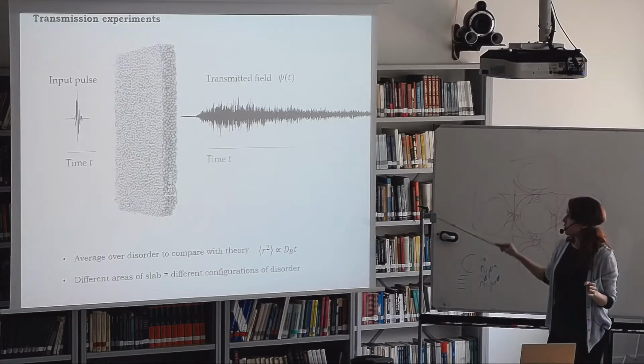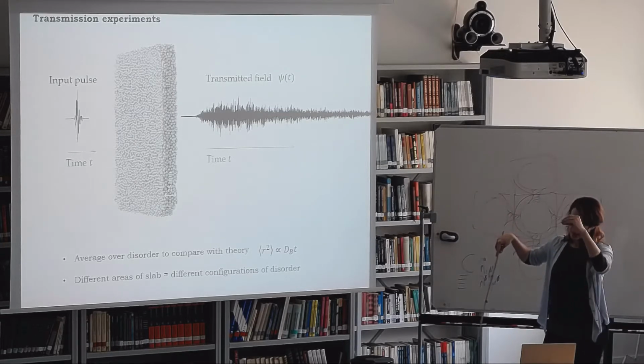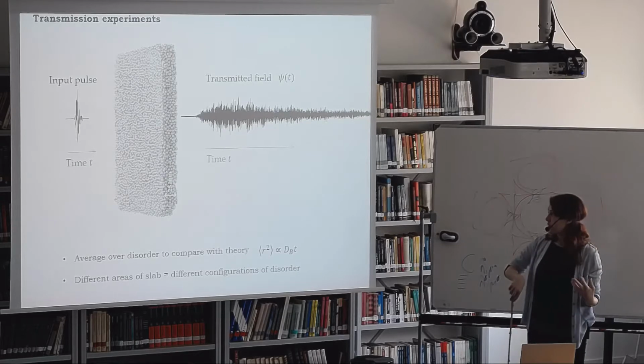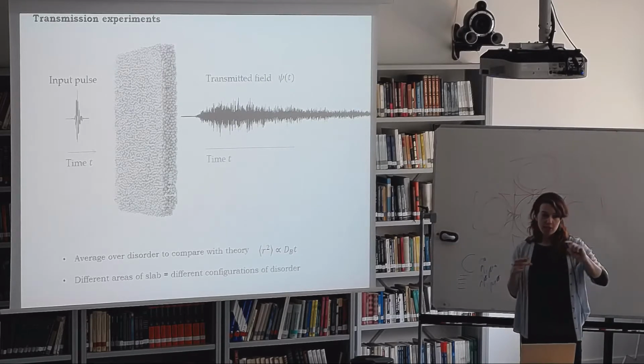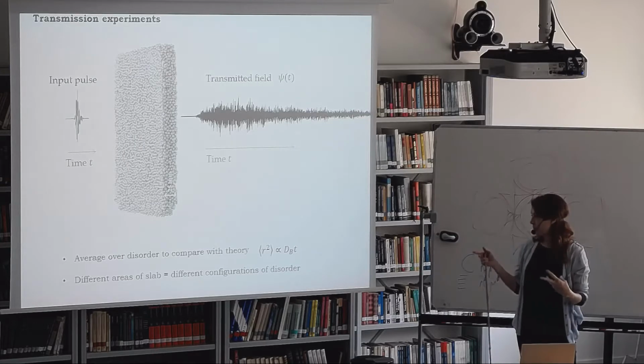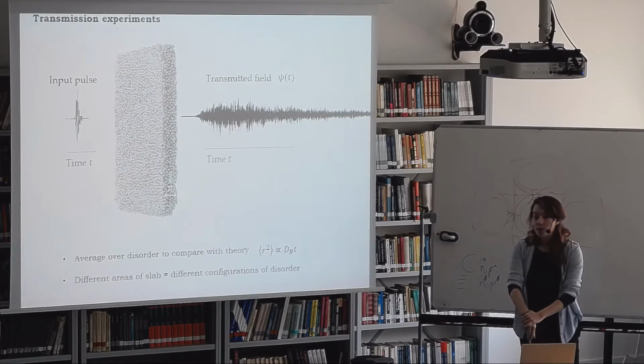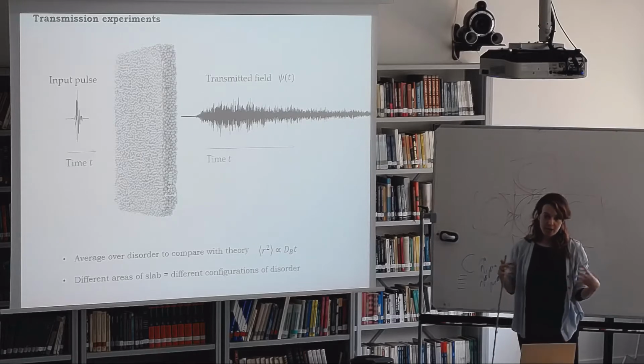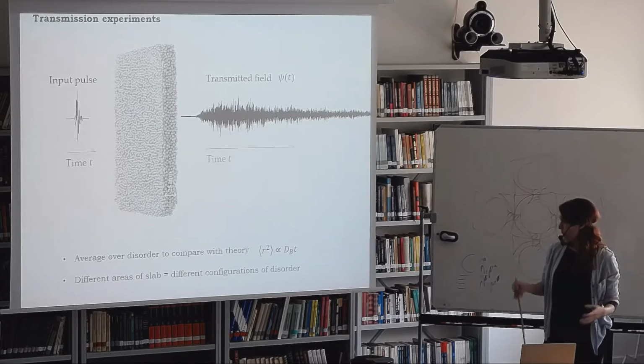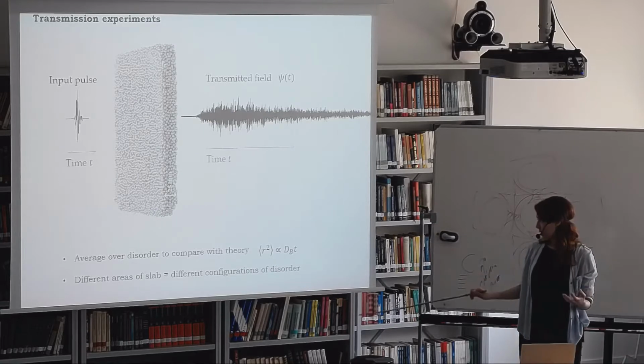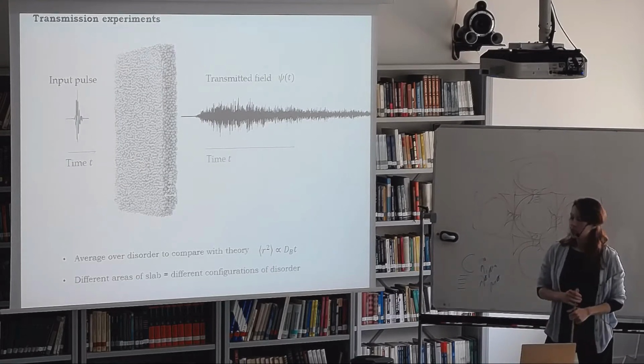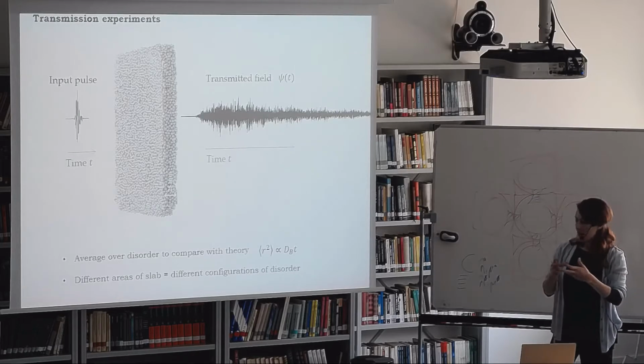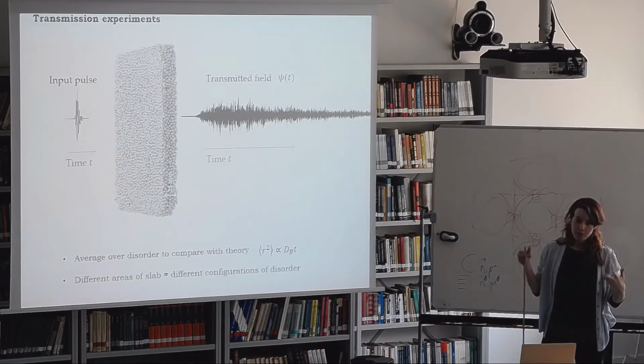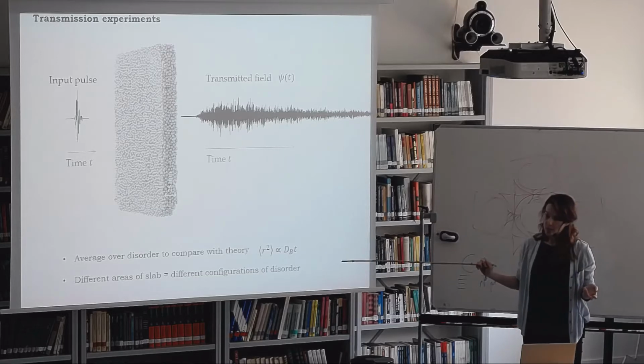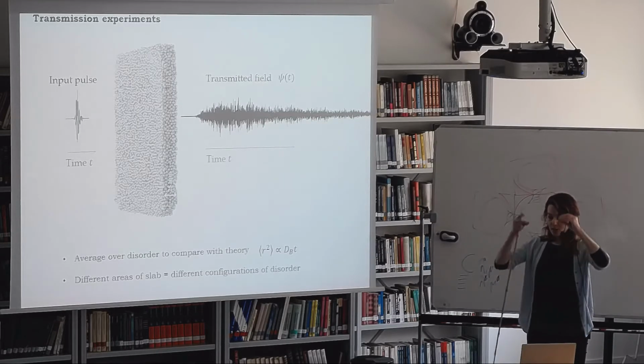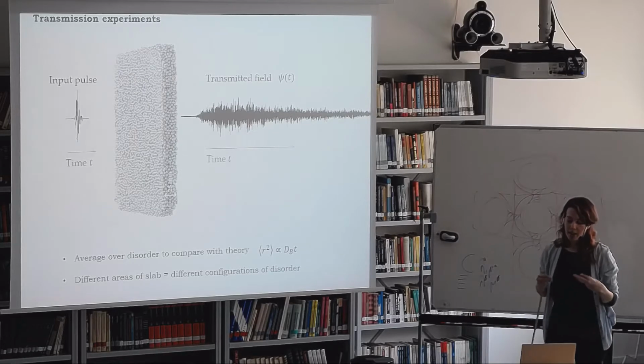Now, this transmitted field would be different if we make the measurement at a different spot inside the sample. And this is because it depends very much on the specific paths that the waves are taking inside the sample. So to be able to compare with theory, in which, as I said, transport is described by average quantities, we want to average over disorder. So this is called a configurational average. Essentially, we want to average what we measure over different configurations of disorder. So for these large slab samples, that means that we can make measurements over different areas of the sample and then average these together.